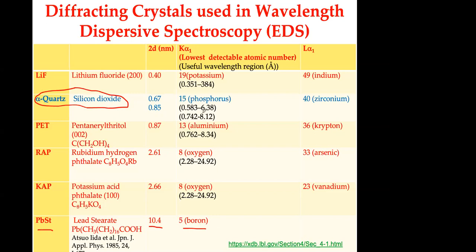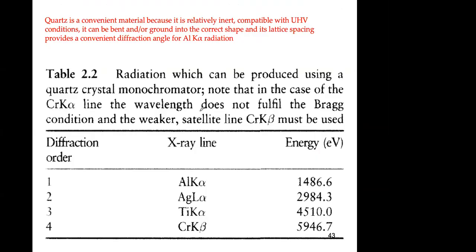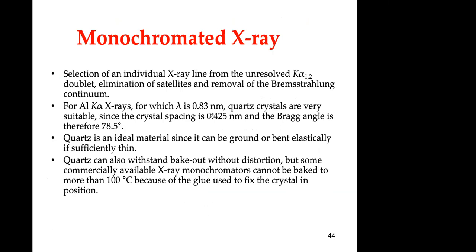a silicon dioxide, quartz, and that's enough for the aluminum K alpha emission. So these are different emissions that the quartz crystal can filter. It can do aluminum K alpha, silver L alpha, titanium K alpha, and chromium K beta. This can be filtered with this crystal. So the crystal is used to filter, to have a monochromatic X-ray. The lambda that goes through in a constructive way following Bragg's law is the K alpha of aluminum, which has a lambda of 0.83 nanometers, 8.3 angstroms.